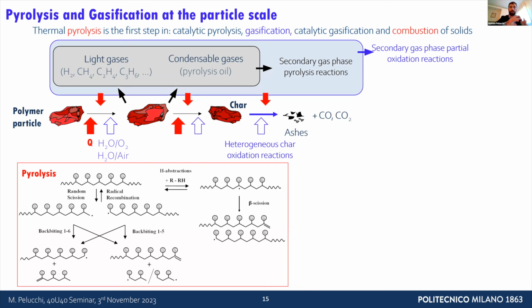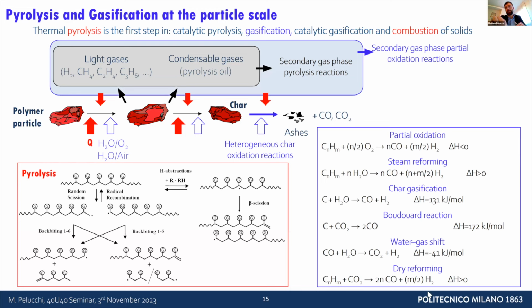On the solid part, on the char that is left, you're able to consume this through heterogeneous char oxidation reactions. These are single-step type reactions typical of gasification systems. As I said before, the balancing between steam reforming and partial oxidation, one endothermic and one exothermic, allows you to reach autothermal conditions.